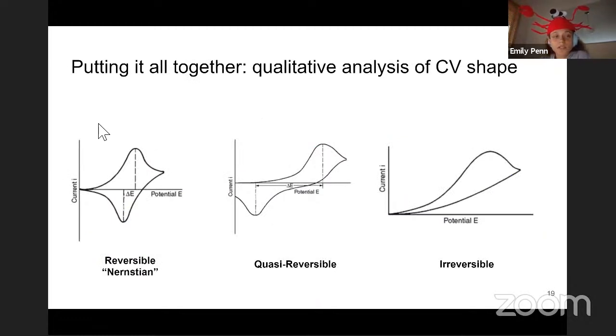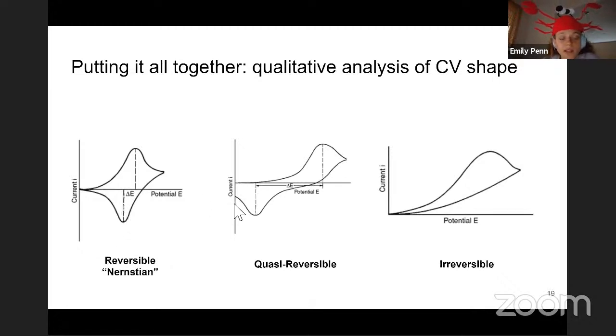So that was an example for ferrocene. Ferrocene is a highly reversible system that's often used as a model, but in practice, the CVs that you may see in the lab don't always look as perfect as that one. First we have what you might see for a reversible, Nernstian reaction. That would be something like ferrocene. And then if we have a quasi-reversible reaction, the rate constants are slower. So we do see some impact of the kinetics, and the delta E here is a lot larger.